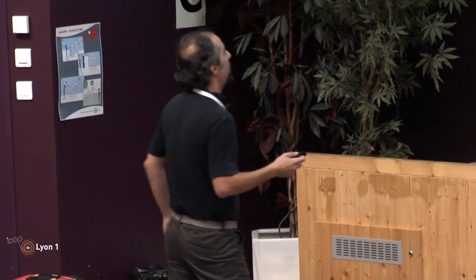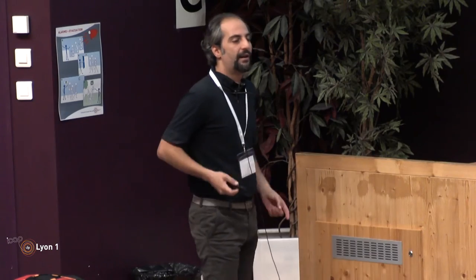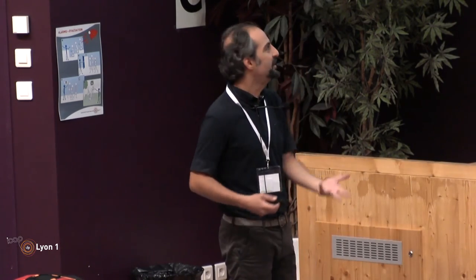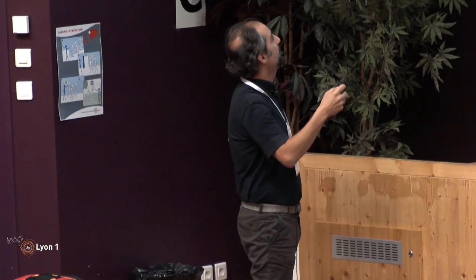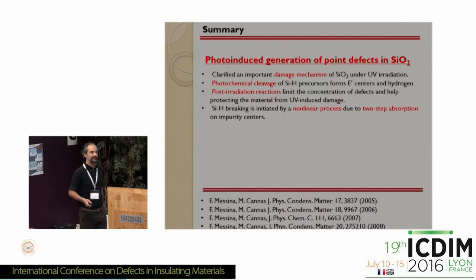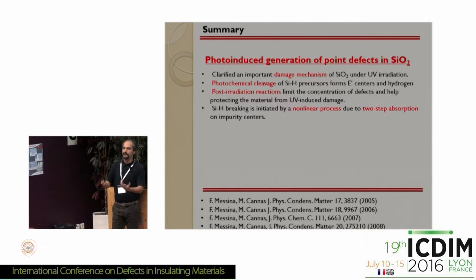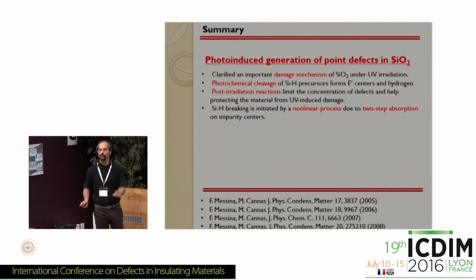Okay, so to summarize, these studies allow us to clarify what we believe to be at least one important mechanism of damage of SiO2 under laser irradiation, which proceeds by photochemical cleavage of SiH bonds already present in the sample and forms defects. An interesting aspect revealed by this study is that the concentration of defects is limited by the fact that after irradiation you have recombination of the defects with hydrogen made available by the same process.